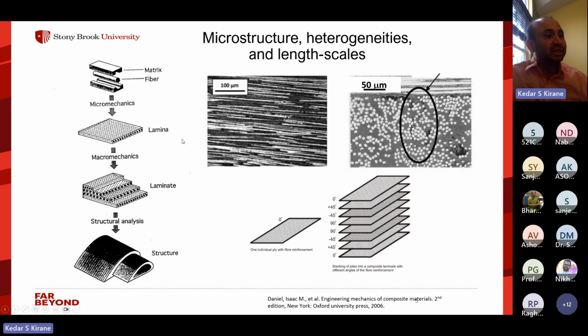So in applications, if you want to mitigate the anisotropy, it is common to use layers running in different directions as shown here, for example, 0, 45, minus 45, 90. And so overall, this stack, which is called a laminate, has some kind of quasi-isotropic behavior. But this layering also leads to another kind of heterogeneity because it's still joining of dissimilar layers. So there are several length scales involved, all the way from the individual constituent level, where there is matrix and fiber, to a single layer, to a stack of layers, which is then used in structures.